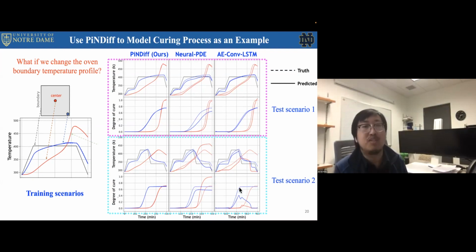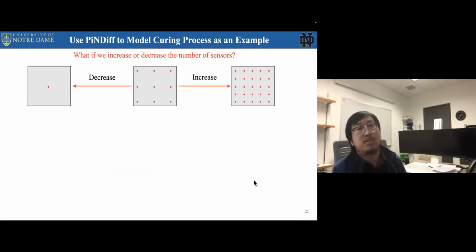If we make things even more challenging, this time we make the autoclave temperature go up and remain constant, go up and remain constant, and go down and remain constant, and go down. This one is quite different from our training scenario, and you can see our models still fit perfectly, right? The generalizability is great for both temperature and degree of cure. But look at the other 2 models; they basically completely fail. Especially the LSTM for predicting the degree of cure gave completely wrong predictions.